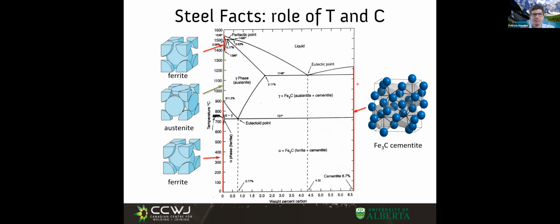The same happens here. If you put too much carbon, it gets to a point where you cannot dissolve any more, and it comes out. In steels, it doesn't come out as just graphite—that happens in cast irons, not steels. Instead it forms this odd crystal structure that is stoichiometrically Fe3C, called cementite. It's a carbide that doesn't have easy slip planes for deformation, so it's a quite hard and brittle material that precipitates.